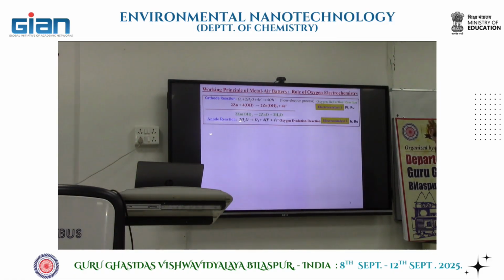one is oxidation and another is the reduction. So if oxygen is getting reduced, then on the other side the metal, basically here zinc, is getting oxidized. So this is a combined oxidation reduction process, but driven by the oxygen partner. And at the same time, in the anode, there is the oxygen evolution reaction, OER in short, where the water molecule basically gets oxidized and results in oxygen evolution, which ultimately releases the 4 electrons.